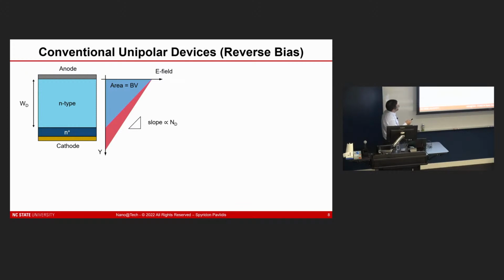So in a conventional unipolar device, like a Schottky diode here, you have this low-doped region underneath your Schottky contact, underneath your anode, and you are distributing the electric field across that. What you're trying to do is basically make sure that you do not hit the critical electric field of your material too early, otherwise you'd have premature breakdown of your device. And the slope of this triangular, or linear, distribution of electric field is proportional to your doping.